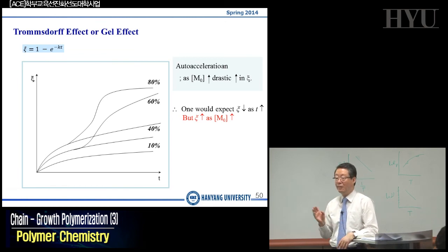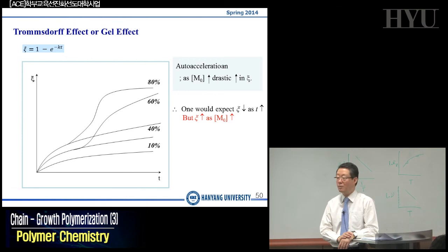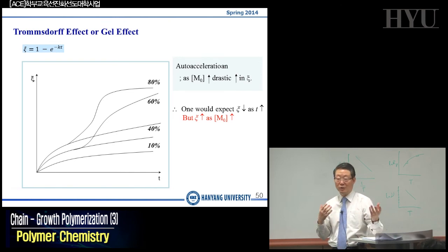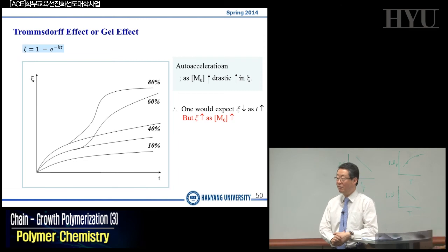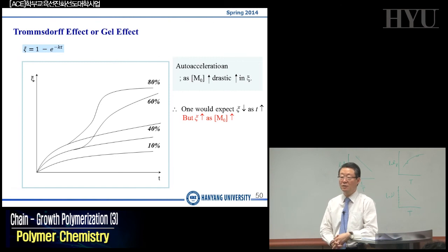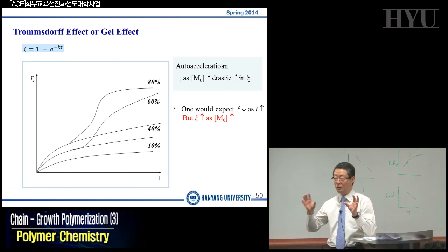Chain transfer — the fourth reaction mode — could be due to a solvent, since the chain transfer coefficient CS is pretty high. CS can be determined by plotting 1/DPN versus S/M concentration. We also talked about temperature effects, and finally the auto-acceleration concept. In the next chapter, chapter 10, we will talk about ionic polymerization reactions, discussing the difference between radical versus ionic modes.